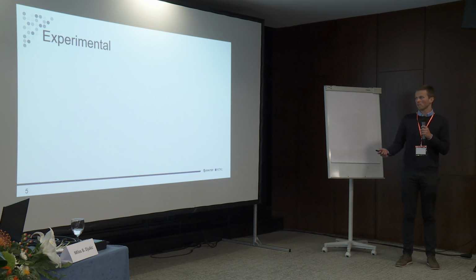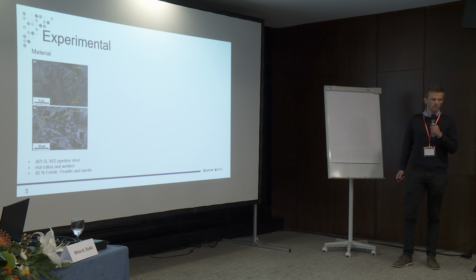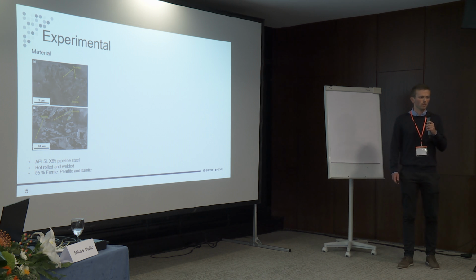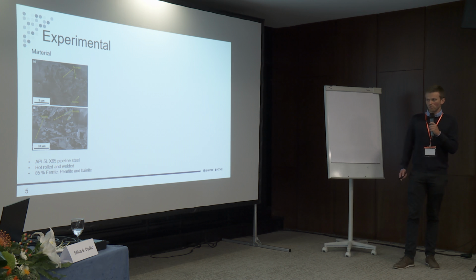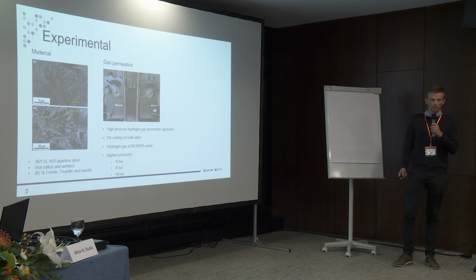So to the experimental work, the steel we investigated is X65 pipeline steel, taken from a hot rolled and welded pipe. The microstructure consists mainly of ferrite, about 85%, and also some pearlite and bainite. So our gas permeation setup looks like this.